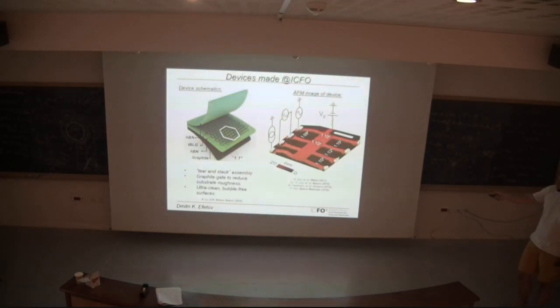And indeed, from our devices, we can measure the twist angle as a function of the whole device range. I will not go into detail, but from transport and from the position of the gaps as a function of carrier density, we can extract the twist angle between every region in the device by measuring different contacts. As you can see, for a typical device we make right now, it's about 10 microns long, 2 microns wide, and the twist angle doesn't change really much. I think this is within the measurement accuracy.